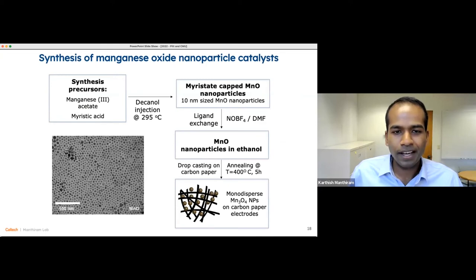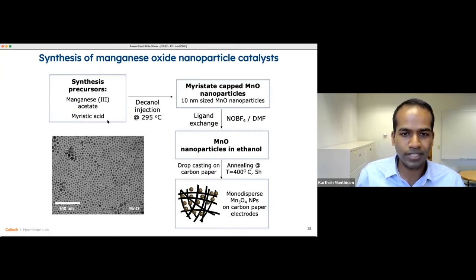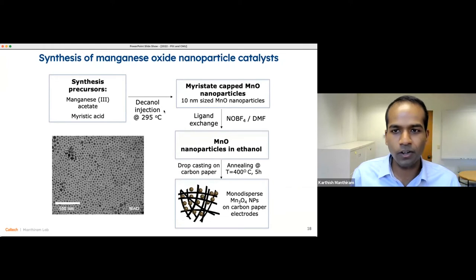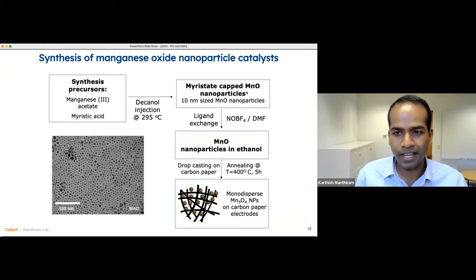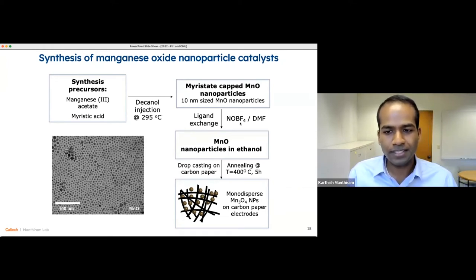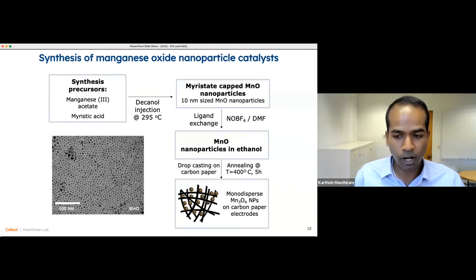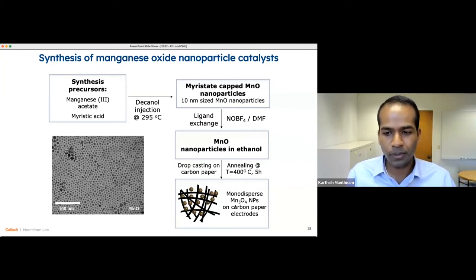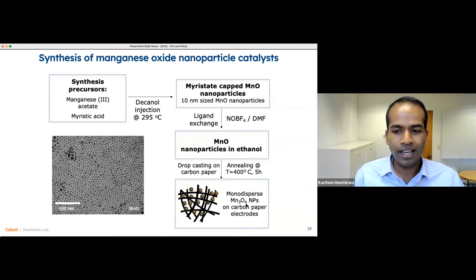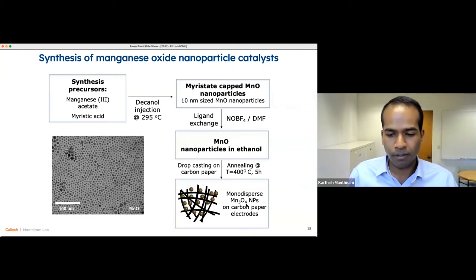So we make manganese oxide nanoparticles from this sort of synthesis protocol, starting with manganese 3 acetate and myristic acid, heating up to 295 degrees centigrade, injecting decanol, making myristate capped manganese oxide, stripping off the ligands, depositing that on carbon paper, and annealing such that we end up with Mn3O4 as our final form for the manganese oxide.